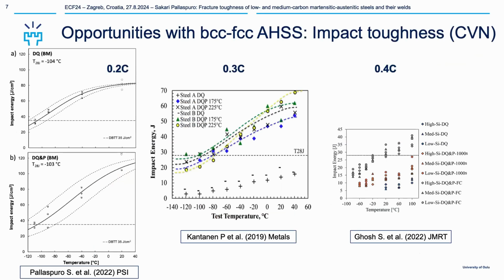So let's look at this first. In the previous work we did, with three different carbon contents from a low carbon range of 0.2 to a medium carbon range of 0.4, we can see with these alloys, looking at the impact toughness transition temperature T28, that they can achieve really good properties, be it directly quenched or partitioned to increase the residual austenite, when the carbon range is low. When you have a medium range of carbon, it already matters a lot what kind of processing you do. It can be fairly good when doing the partitioning treatment, while with just direct quenching it will be completely brittle. And if we go up to the 0.4 carbon range, it doesn't matter much what you do, it will not be very tough.